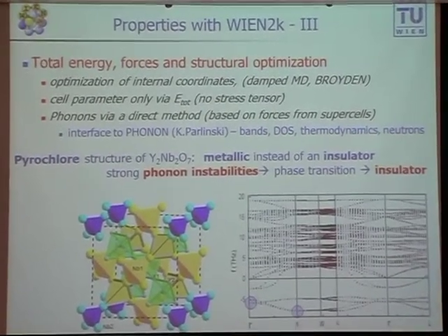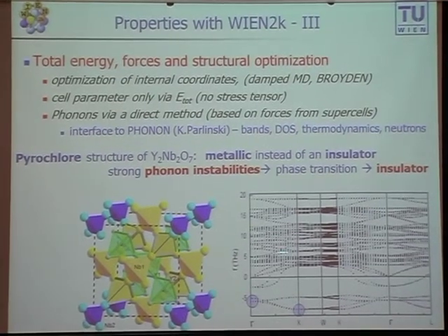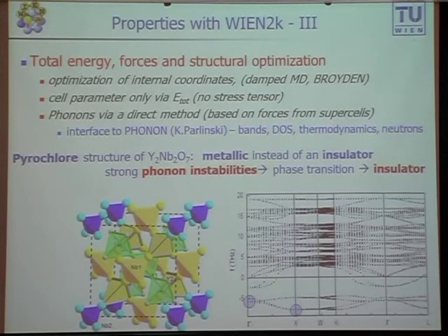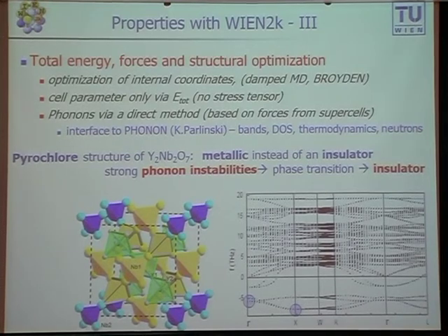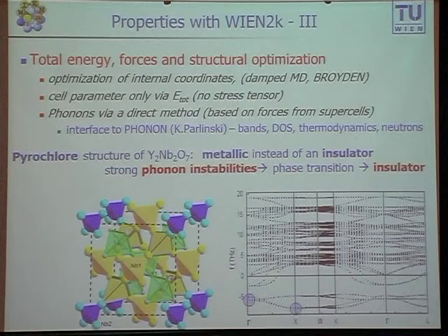That's it. So you cancel the imaginary frequency only at high symmetry points? Everywhere. But the supercell calculation? Yes, but Gamma is interpolated or? It's interpolated. It's using this and gets the force constants. So you do a supercell, but then you get the force constants, and if the force constants are falling off to 0 at some point, with this you can then calculate the phonons at every Q point. Yeah.